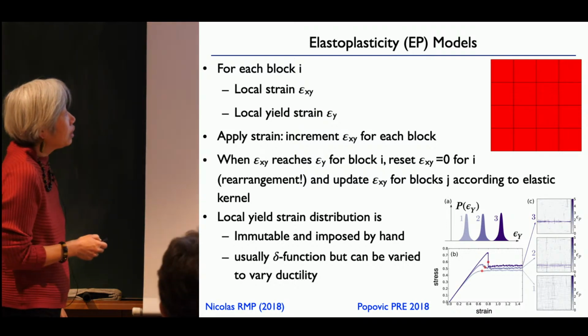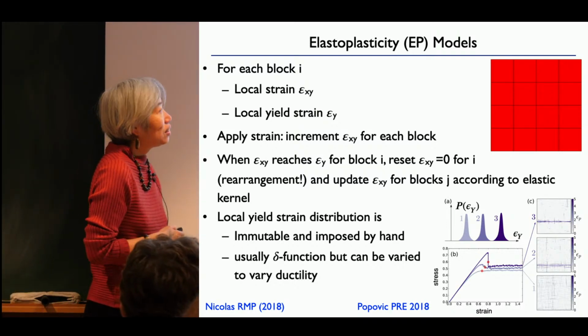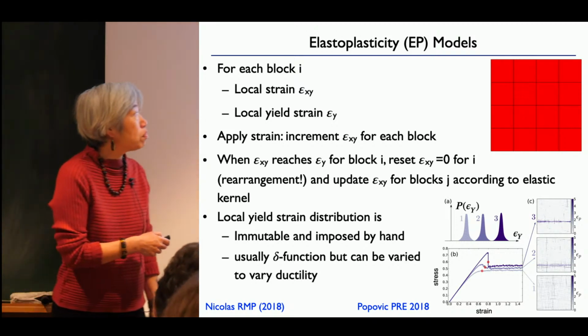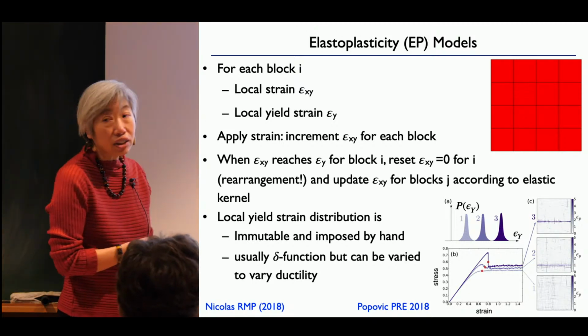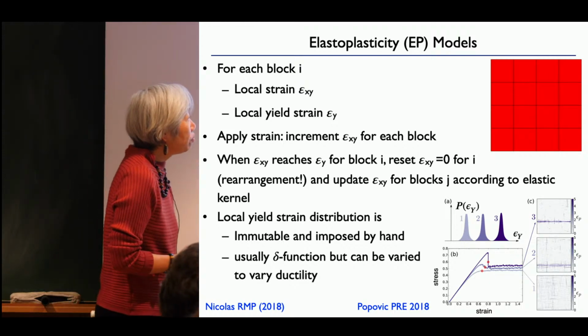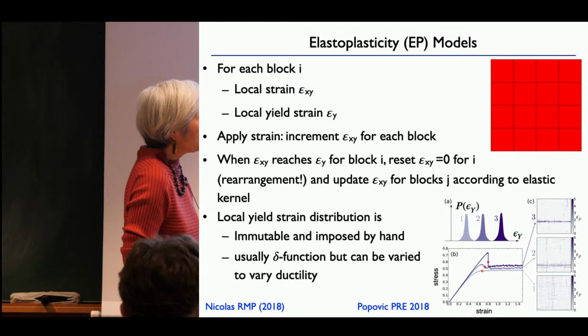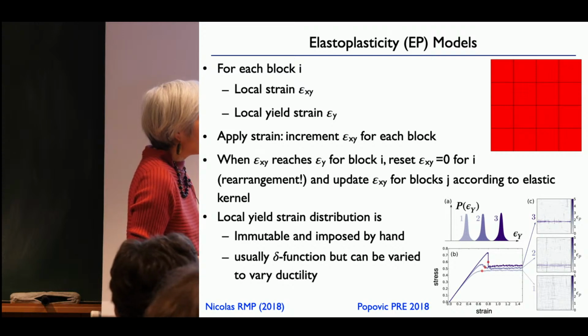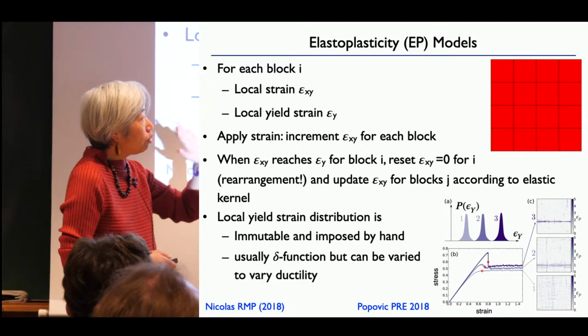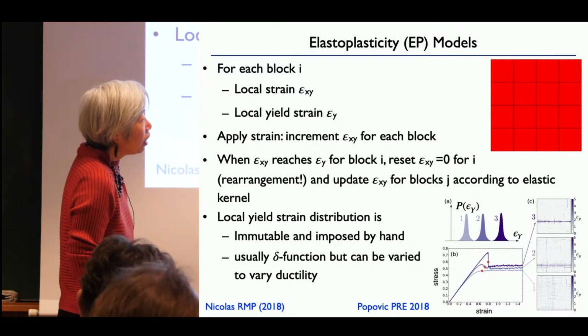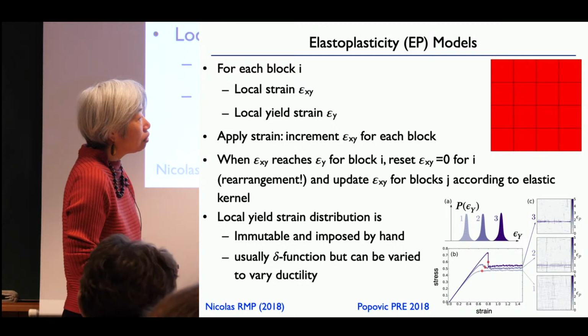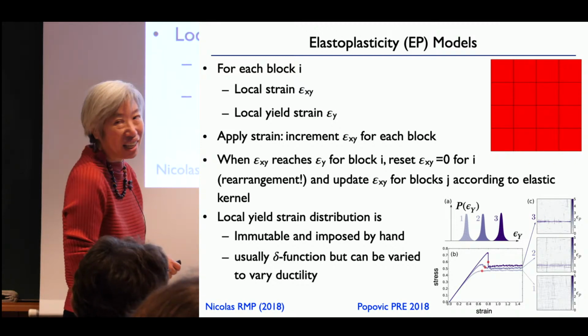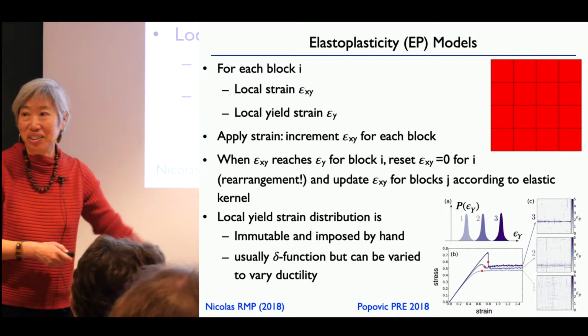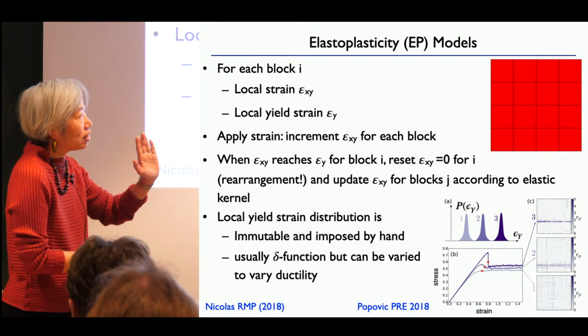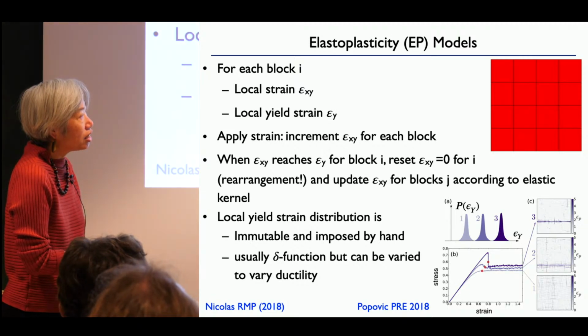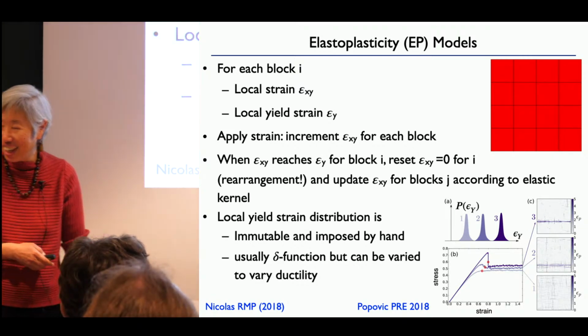And in most models, the local yield strain distribution is fixed. It never changes, and it's imposed by hand. Now, it's usually a delta function, but you can do something more fancy. And what was shown recently in this work from Mathieu Viart's group is that if you just change the magnitude of that yield strain distribution that you put in by hand, you can get ductile or brittle behavior, depending on the magnitude of that yield strain. The bigger this yield strain is, if you push it out to this dark curve, which has the highest yield strain, then you see brittle behavior.